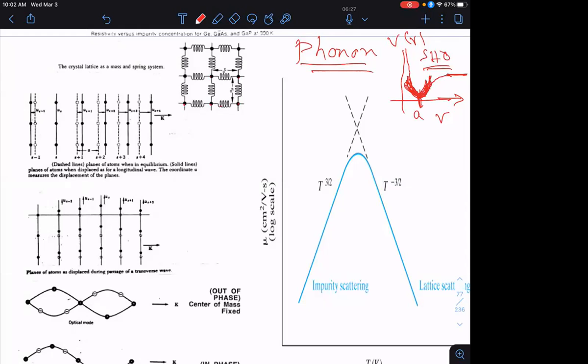Okay. Now, once you postulate these springs, then you can imagine you have these atoms in planes which might vibrate like this. Now, if they vibrate like this, these springs will get squashed. Okay. And the restoring force will cause these atoms to bounce back, okay? And it basically will oscillate back and forth. Now, there are different vibrational modes. So for example, on the top figure, I can have a wave of these vibrations propagate to the right, and the corresponding displacement patterns of these atomic planes is shown over here, and these planes oscillate back and forth, okay? Where in this particular case, the atomic displacements are in the same direction as the wave propagation. These are known as longitudinal phonons, okay? On the other hand, the atoms themselves might vibrate in a direction perpendicular to the direction of the wave propagation. These are called transverse phonons, okay?